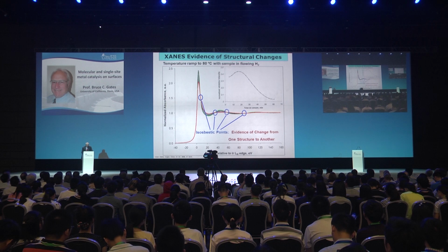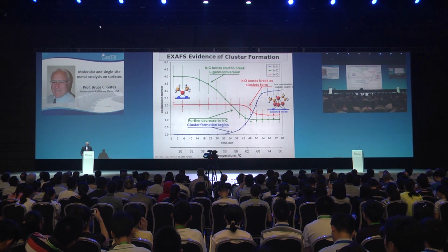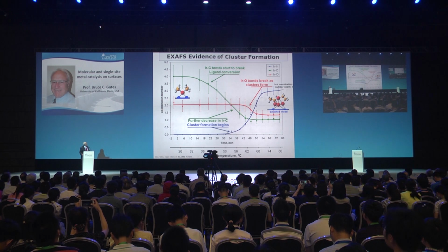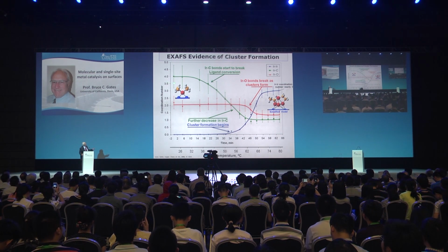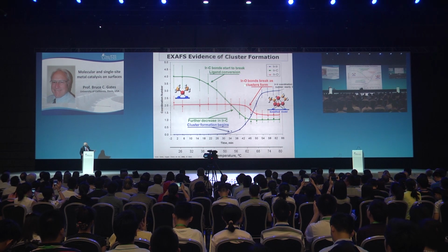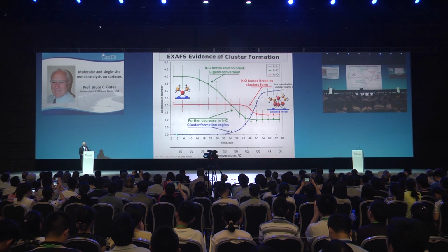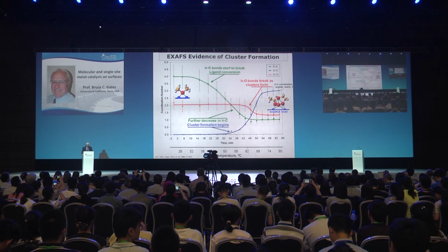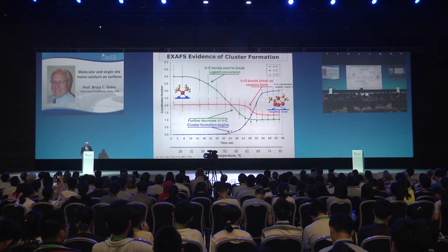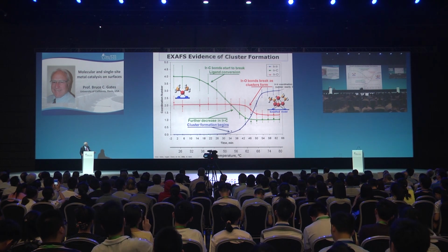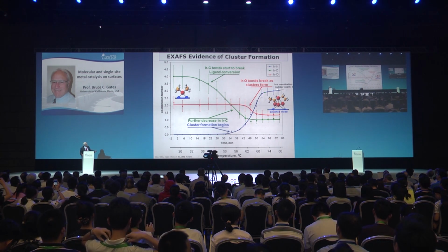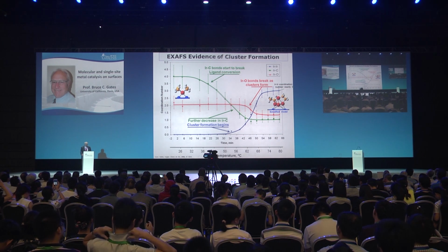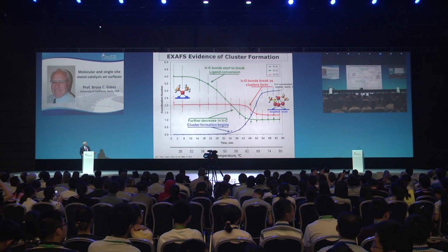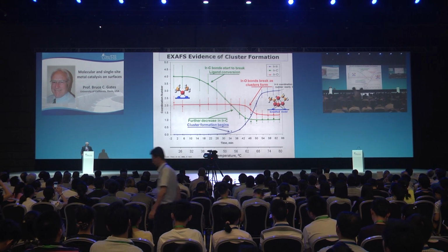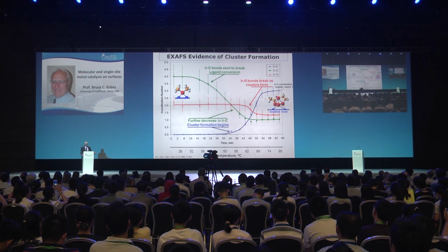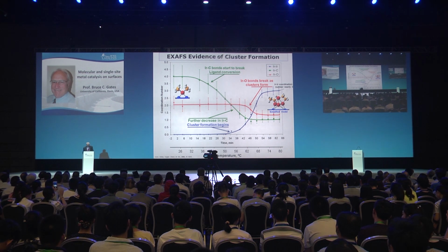What does the XAFS show? Let's look at the iridium-iridium coordination number. It starts as a mononuclear species, so the iridium-iridium coordination number is indistinguishable from 0. During this treatment, clusters grow, and they grow until that coordination number becomes nearly 3, which corresponds to a tetranuclear cluster. As that's going on, we're breaking iridium-carbon bonds, making ethane, and doing reactions that are organic in the coordination sphere of the metal.